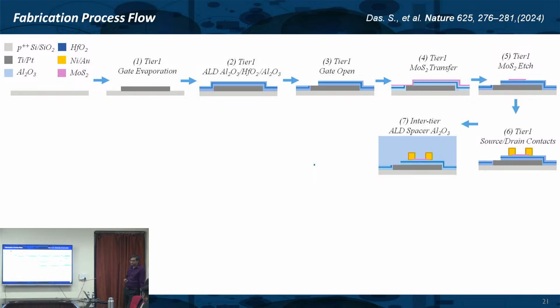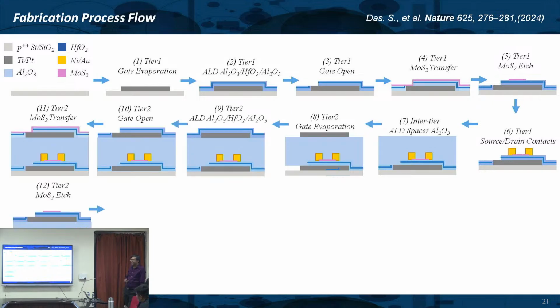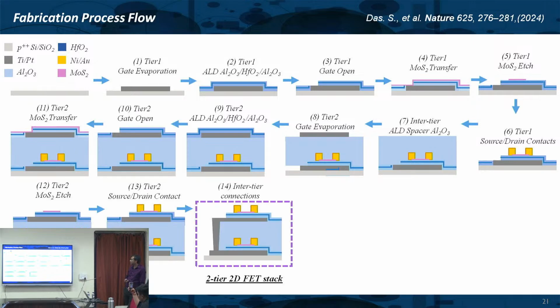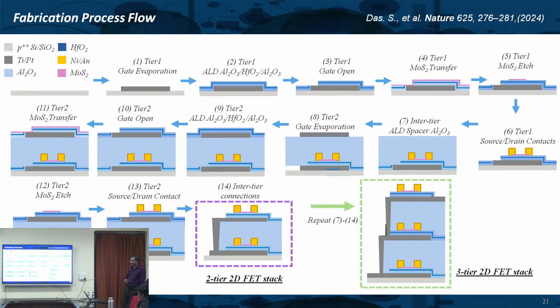Then you simply repeat: again gate evaporation, again alumina ALD, again gate open, again transfer, again etch, right? Again source drain contact, and then you get to tier 2. And then you keep repeating it, and you get tier 3. At that point, you have to start etching the inter-tier dielectric and start doing these vias. But these are no longer through-silicon vias, and these vias are now very small, and they are connecting transistor to transistor, which we could not do with the heterogeneous packaging industry. Make sense?